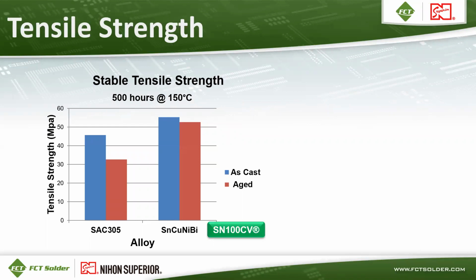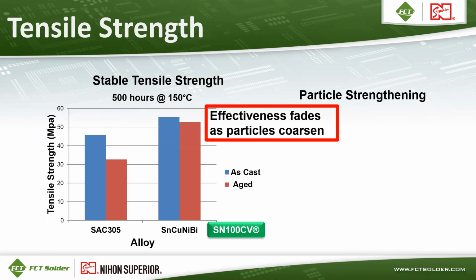Here's a chart of tensile strength for SAC305 and SN100CV alloy. These alloys were tested initially, which are the blue bars, and then they were tested after aging, 500 hours at 150C. You can see SAC305 lost a lot of tensile strength with that thermal aging, whereas SN100CV was fairly stable with that thermal aging.